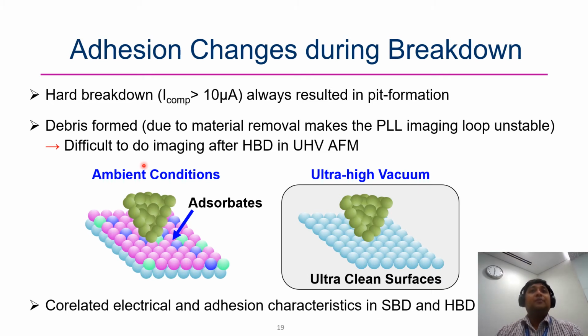So instead, what we relied on was adhesion, because since we were in ultra high vacuum, the surface remains clean for a very long period of time. And we also know that adhesion is very characteristic to the two surfaces in contact. So for example, when we have hBN in contact with the metal, it will be very different compared to when we have two metals in contact. And that is how we use this approach to quantify the soft breakdown and the hard breakdown using conductive AFM.